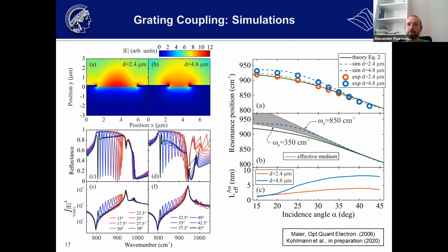For this forward propagating mode, it fits in frequency, but because there is no shift in the resonance as you change the incident angle, also not predicted, I don't actually have experimental proof that it's a polariton. It might just as well be a localized mode. And the test would be, and I've seen Stephanie Lau in the audience, she's done that a lot, if instead of changing incident angle, you change the period of your grating and run a series of different periods, this mode should shift also.